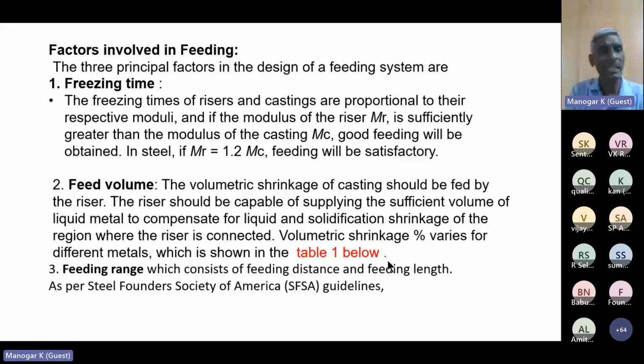Factors in feeding, three principles. One, freezing time. The freezing times of riser and casting are proportional to their respective modulus. If the modulus of the riser is sufficiently greater than the modulus of the casting, good feeding will be obtained. Two, feed volume. The volumetric shrinkage of casting should be fed by the riser. The riser should be capable of supplying sufficient volume of liquid metal to compensate the liquid and solidification shrinkage of the region where the riser is connected. Volumetric shrinkage varies for different metals, which is shown in the table. Three, feeding range, which concerns feeding distance and feeding length.